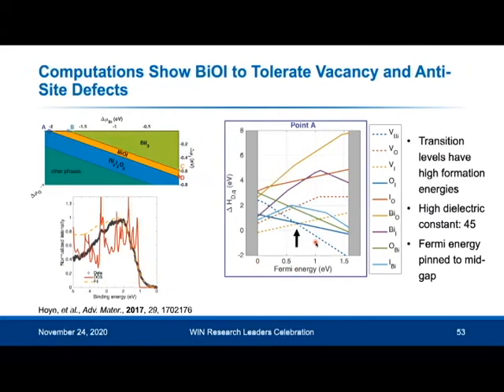And as a rule of thumb, if the formation energy is above 1.5 electron volts, then the concentration of the defect is so low that you may as well neglect it. So we only are looking at a small handful of these defects here, the bismuth vacancy, the iodine vacancy, and these two anti-sites here. And the slope of these lines represents the charge state of the defect.